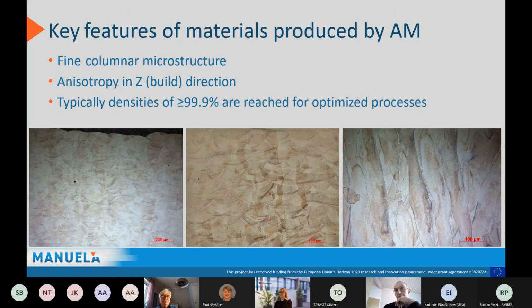Next slide. So for those who are material scientists, key features of materials produced by AM, I just want to show this. After we get a fine columnar microstructure built, we can get certain anisotropy in the build direction. But it's important to understand that if we have the processes under control, we typically get densities of well above 99.9 percent and even better relative density. So people believe in some cases and say this is material where you have a lot of pores. This is not true. This is hardly at all true. The technology today is such that, if we have the processing under control, we build basically fully dense material.